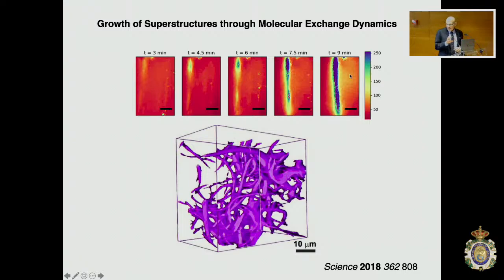We found that within minutes, as you see at the top, in about 9 minutes, this very strong fluorescence appears in front of your eyes because we put a fluorophore in the DNA. So the fluorescence concentrates. Initially you don't see it because there are very few molecules with DNA, therefore the fluorescence is very weak. But suddenly, in certain spots, the fluorescence is super strong, and you see it happen over minutes. And so what is happening is that the DNA-containing molecules walk.